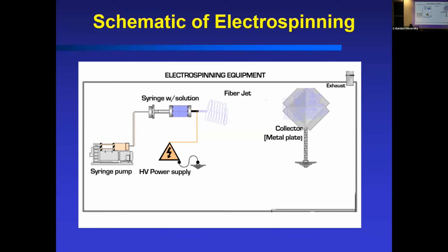So we use this process of electrospinning, which is shown here. Other labs use it. We've been able to really optimize this process such that we can control those fiber dimensions, as well as orientation of fibers. And so it's a fairly simple process. Again, where you're applying this high voltage to your material of interest, polymer that may be dissolved, or composites that are dissolved in some solvent.